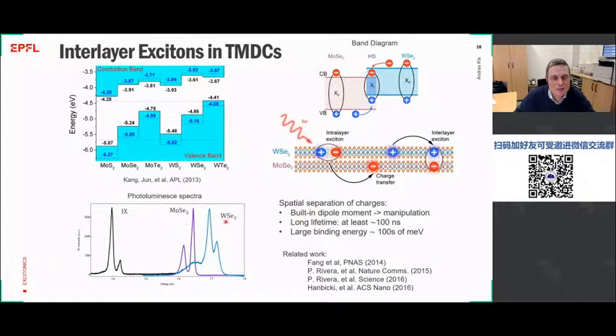So if you take a heterostructure of MoSe2 and tungsten diselenide, these would be the regular photoluminescence peaks of the individual materials. But if you make a nice heterostructure with a clean interface, then these peaks almost completely disappear. And you see on the lower energy a new set of peaks which corresponds to the creation of interlayer excitons. This pretty much happens because this process of breakup, dissociation, charge transfer, and creation of interlayer exciton is much faster than the normal lifetime of just the intralayer exciton in these heterostructures. So they break up and rearrange themselves before they can emit at the wavelength of the individual material.